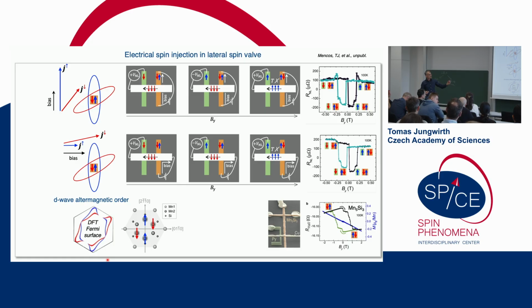But in thin films, and also there is a structural transition in bulk, which we don't see in the films, because films are clamped to the substrate, etc. So there's a fairly long story. But anyway, there is a lower temperature phase transition into a non-collinear, non-coplanar phase, which Libor likes very much, because it's a p-wave magnet. Okay? But do they have moments in the other two manganese in the lower phase? In the lower phase, they become moments also in those ones.